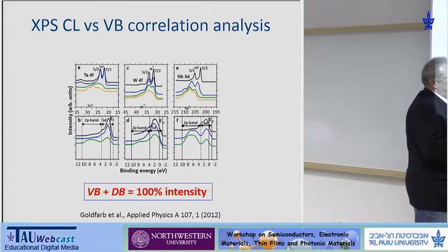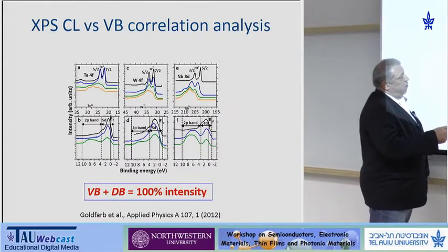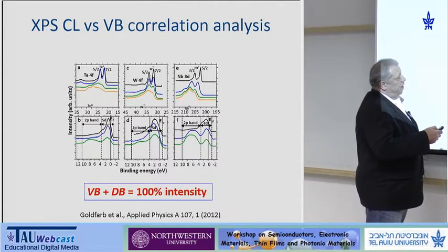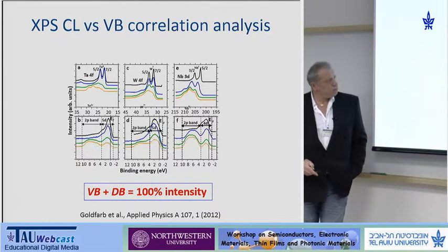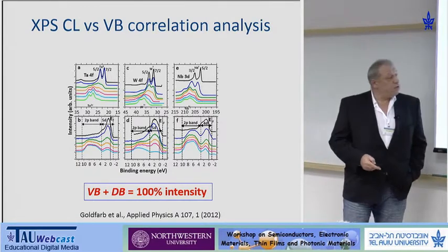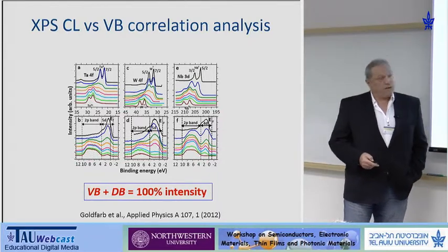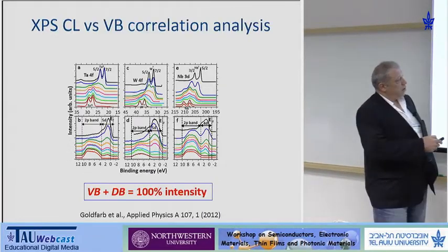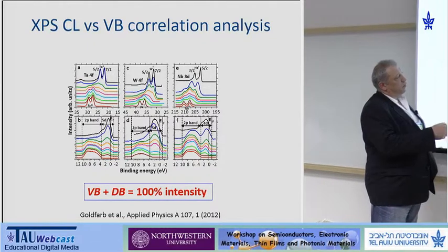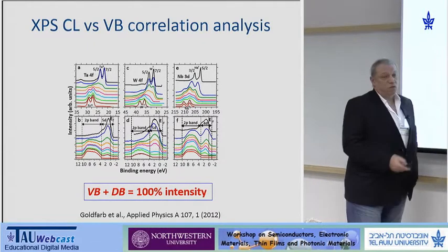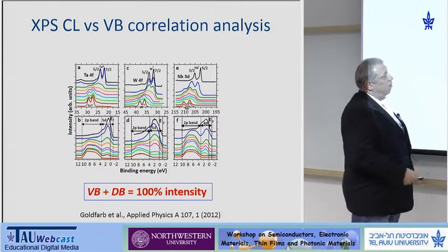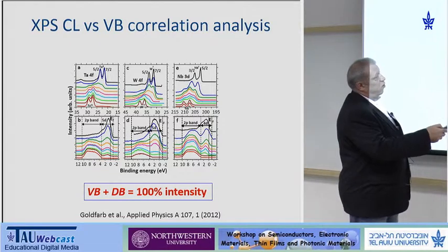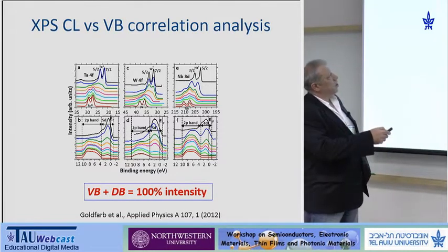And at the same time, what we see in the electronic structure is that this d band goes down, and as it shrinks, we see the formation of a valence band that grows. This process continues until we get a fully oxidized layer. Here, you see we no longer have that d band. We only have the valence band that's supposed to be in an insulator, and no more intermediate oxides. We only have the finite terminal oxide: so pentoxide, pentoxide, and trioxide.